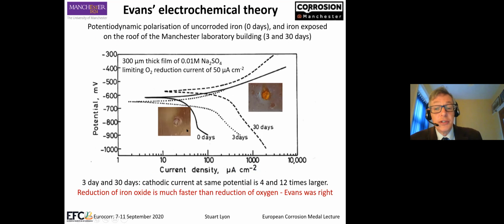And you can see now why I wanted rusty electrodes, small electrodes on the surface of the sample. Here is our shiny uncorroded system. This is freshly polished. So this is the oxygen reduction reaction. It's about 50 microamps per square centimeter, which is about right. For a small electrode, you have radial diffusion, which increases the nominal rate. However, on a rusty surface, our corrosion rate, or our cathodic current at the same potential, is much, much higher. And the only reason that can possibly be is that the reduction of iron oxide is kinetically a lot faster than the reduction of oxygen. So Evans was not able to do this experiment in his day, in the 1960s, but he was right. He had great prescience.